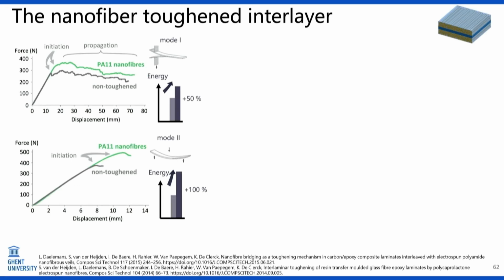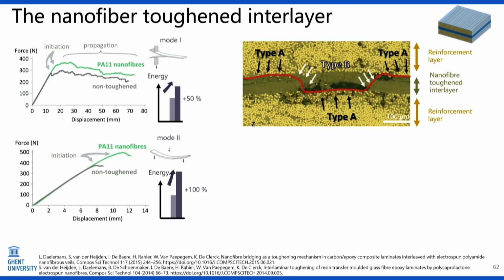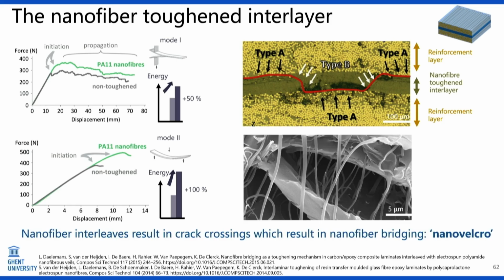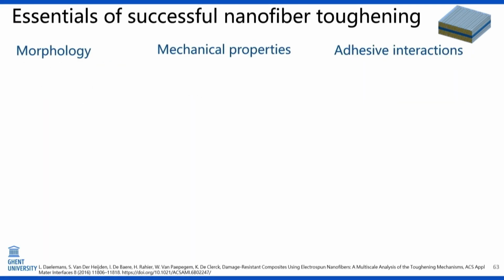For that we looked at the bilayer here with the matrix in between, and indeed we tested these materials in both mode 1 and mode 2, and for both we have an increase in initiation of cracks and in propagation. And the reason is, if we look at the crack path, at the cross-section of a tested sample, then the crack path crosses this interlayer a couple of times, and it's at these crossings that this nano-velcro effect becomes effective. So that works, but it's not as easy as it seems.